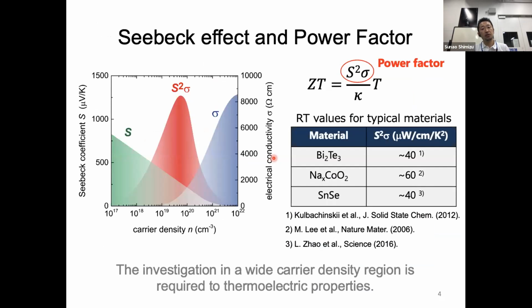The property of a thermoelectric material is evaluated as the ZT value or power factor S squared sigma. S is the Seebeck coefficient and sigma is electrical conductivity. Here kappa is thermal conductivity and T is temperature. This ZT or power factor changes drastically with changing carrier density. This is a schematic figure. When we increase carrier density of materials, the Seebeck coefficient decreases gradually like this. On the other hand, the electrical conductivity increases like this, so the power factor S squared sigma shows a maximum at some carrier density. So when we investigate thermoelectric materials or thermoelectric properties, we have to systematically control carrier density.